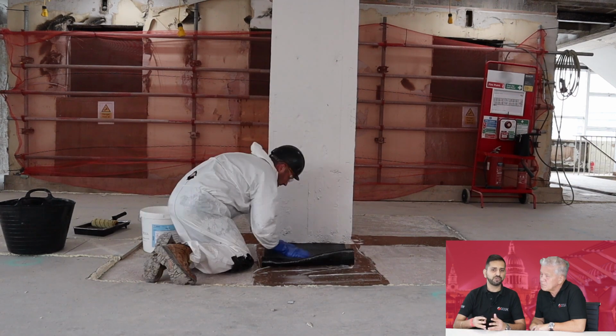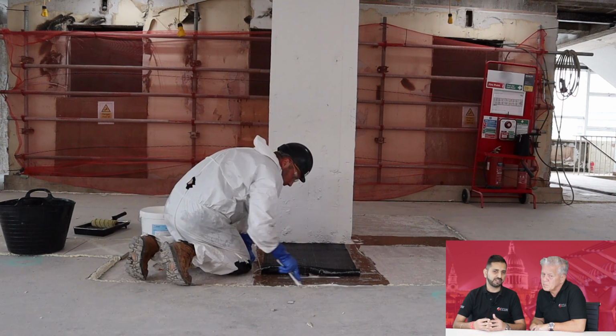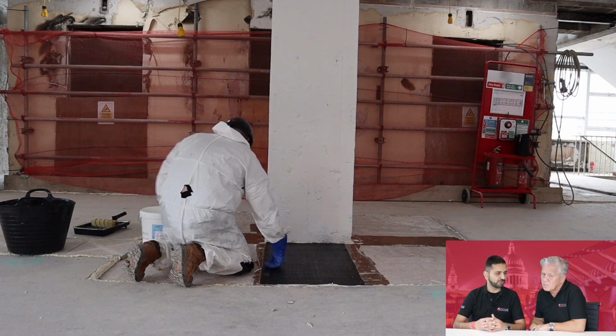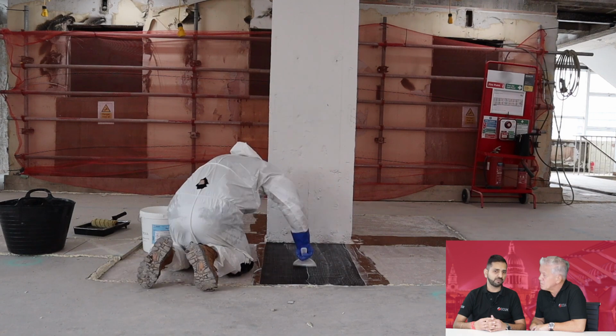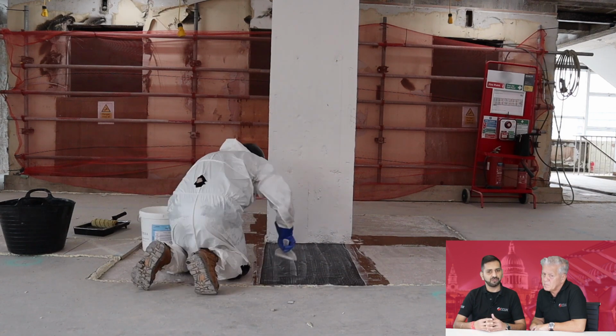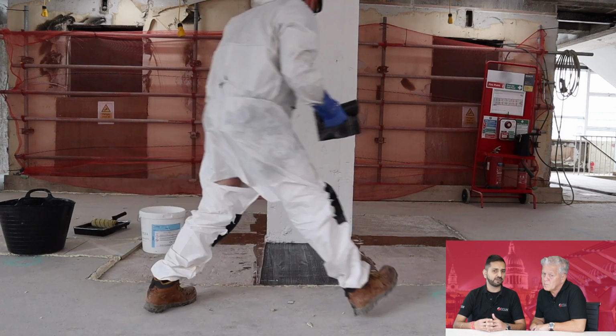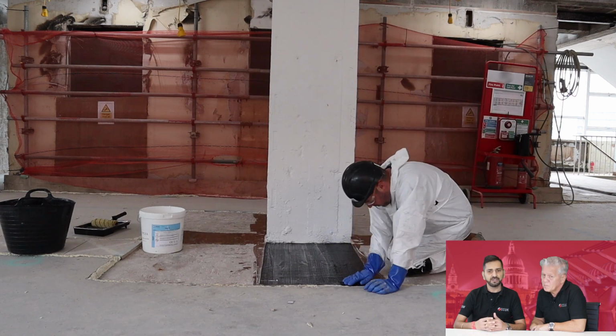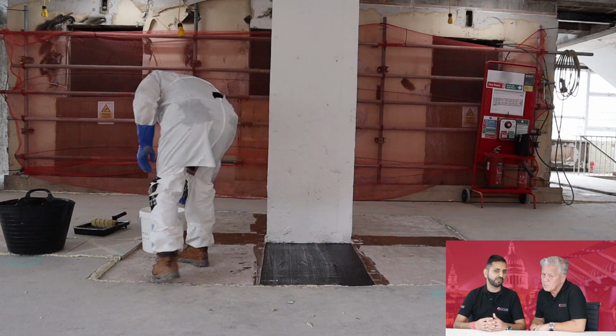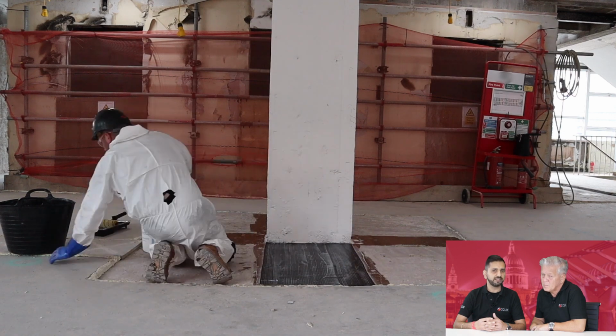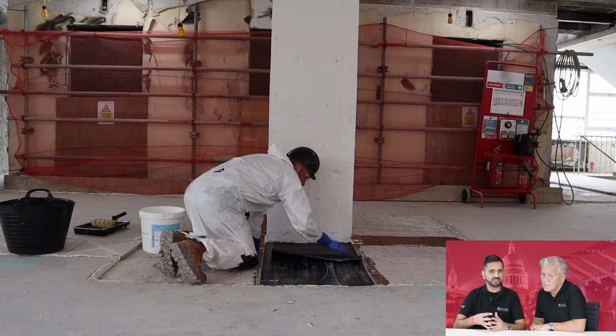In dry layup, you just prime the concrete using epoxy, then you try and patch a dry fiber with your hand on top of it, and then coat another layer of epoxy on that dry fiber. In doing so, you cannot guarantee 100% resin impregnation through every fiber, and that dryness will lead to a debonding or delamination failure. To avoid that, application needs to be wet layup. So that's how we do the application.